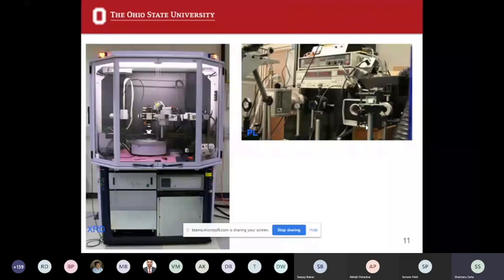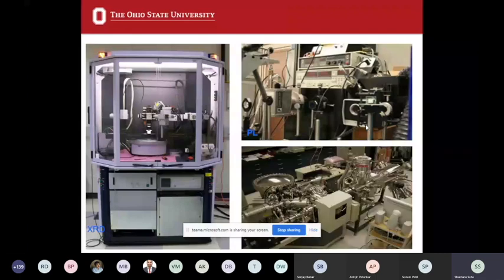And this is another setup, which is SIMS, that is secondary ion mass spectroscopy. If you would like to intentionally incorporate some material in your film, for example, if you would like to dope, then you can also measure the doping concentration with the help of SIMS, which can ensure what kind of doping concentration is there in your film.